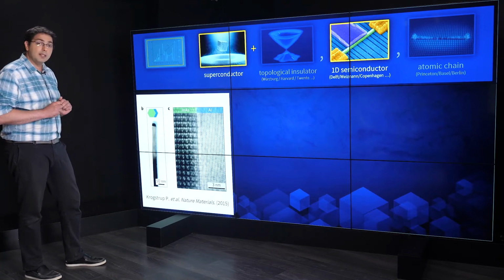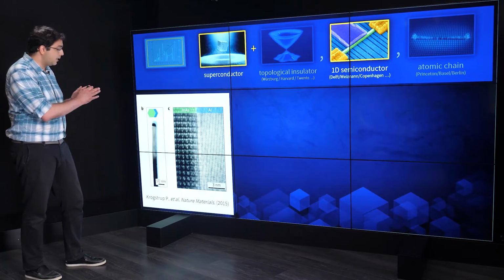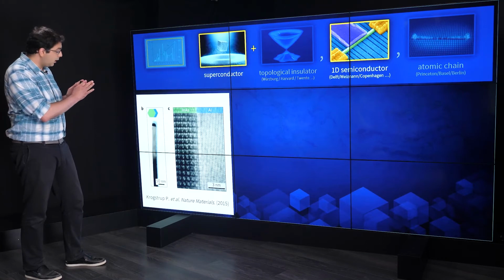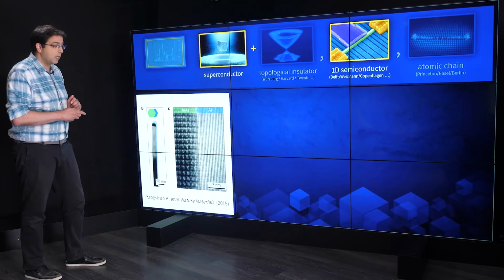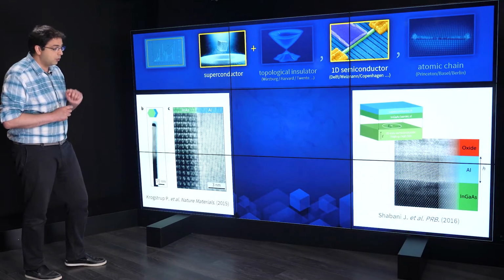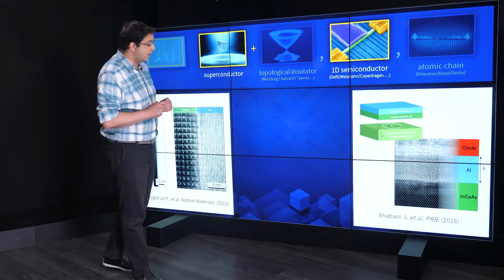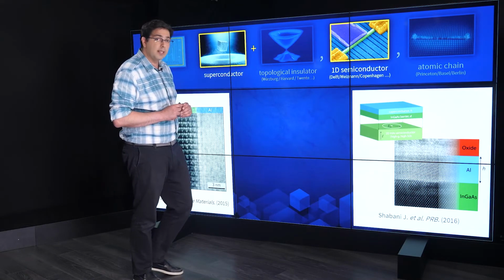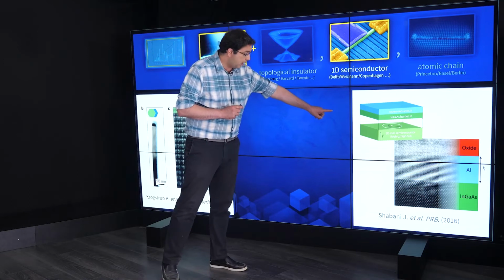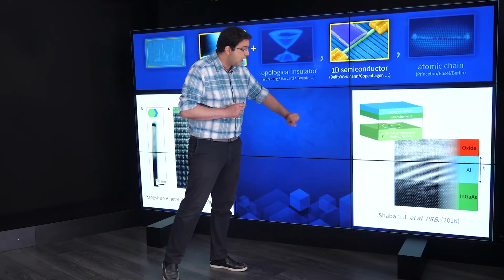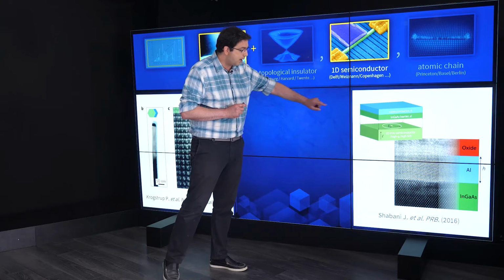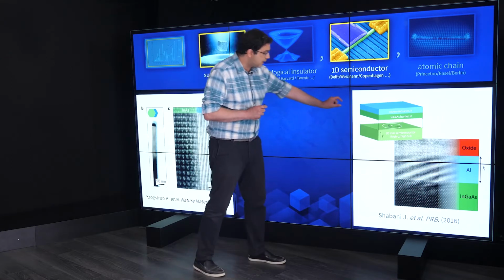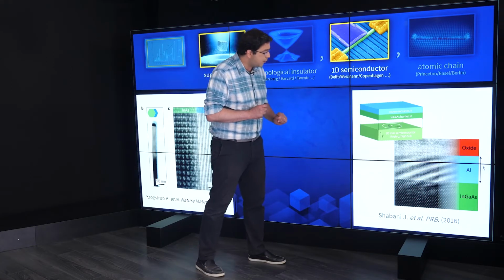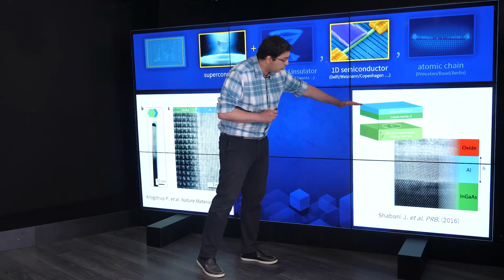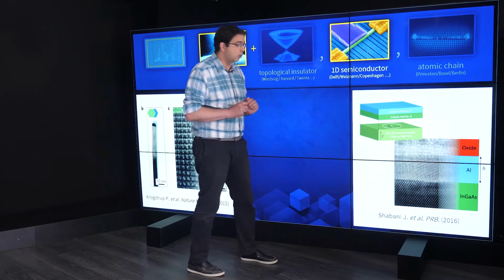But another interesting development is that this epitaxial growth not only went in the direction of 1D, it also went in the direction of 2D. And this is by Shabani et al. What you can see here is a 2D indium arsenide quantum well, which is again proximitized by aluminum. There is a small barrier here, but that doesn't matter. You proximitize the indium arsenide quantum well with the superconductor.